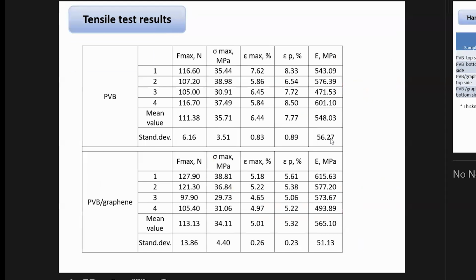Okay. Here we have presented the tensile test results. We have done tests on 4 specimens of each kind, and we have taken the mean value with standard deviations. What is important to note here: tensile strength is actually similar for the neat and nanographene modified polyvinyl butyral, but the elongation is pretty different. What can be observed is that when we add graphene, the elongation at break and maximum elongation are smaller for the graphene modified polyvinyl butyral, because each particle, each nanoplatelet of the graphene represents actually a discontinuity in the material. So this is why it elongates less than the neat material.